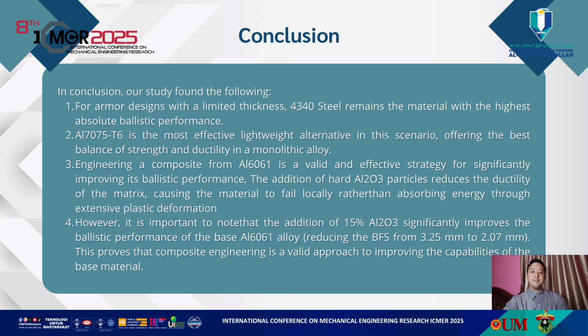The conclusion is that for armor designs with limited thickness, 4340 steel remains the material with the highest ballistic performance. Aluminum 7075 T6 is the most effective lightweight alternative in this scenario, offering the best balance of strength and ductility in a monolithic alloy. Engineering a composite from aluminum 6061 is a valid and effective strategy for significantly improving its ballistic performance.